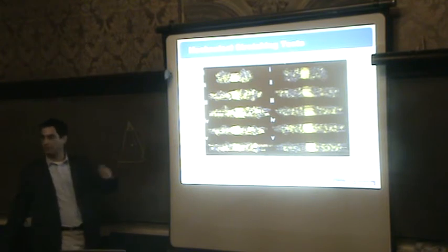And then we can take the most representative structures we have and basically stretch them. And as you stretch them, you can see clearly that there is more crystallization occurring due to the formation of new hydrogen bonds in between the strands. And this provides higher stiffness as you stretch it more and more, plus you're stretching the covalent bonds more, and therefore you have a highly nonlinear kind of behavior. This is observed to a lesser extent in the case of proline, which again causes breakage of the crystalline domains.